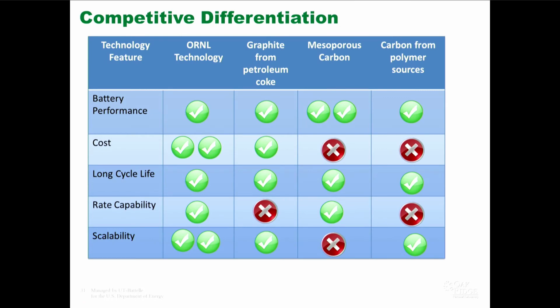So let's look at the competitive differentiation between our technology and the technology that's known outside. I have a table comparing the technology features like battery performance, cost, long cycle life, rate capability, and scalability. The ORNL technology, the first column, is the one I talked about today. We are comparing it with graphite from petroleum coke, that's a standard process, or mesoporous carbon, which is well known in the literature, and also carbon from polymer sources or other sources, plastics. The battery performance is comparable, I would say, to graphite or any polymer source. However, mesoporous carbon may have higher performance than this standard graphite, but cost-wise, we are going to be the cheapest compared to any technology that's known right now with respect to graphite powders for battery electrode materials.